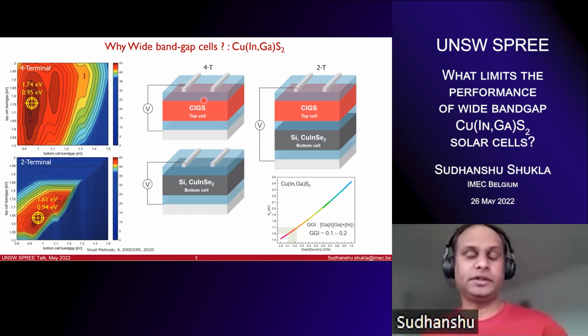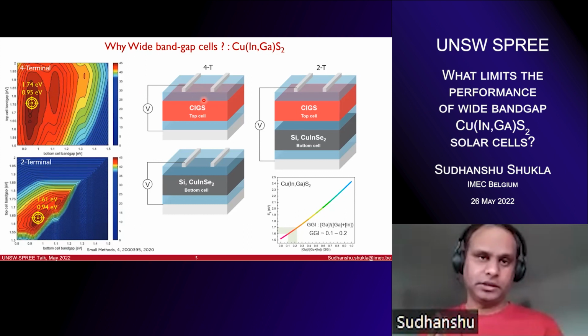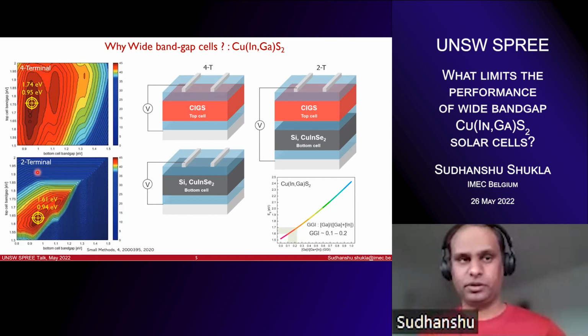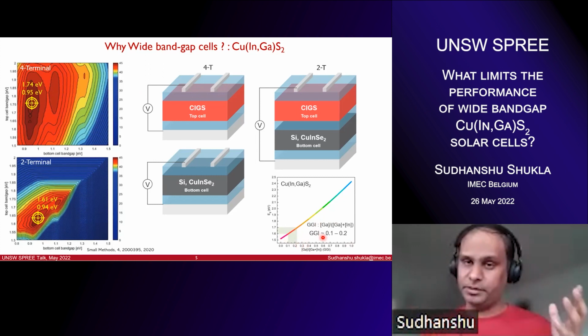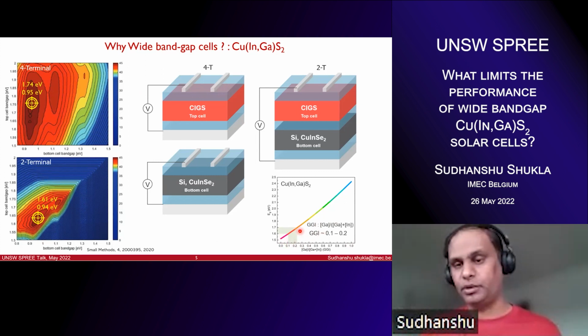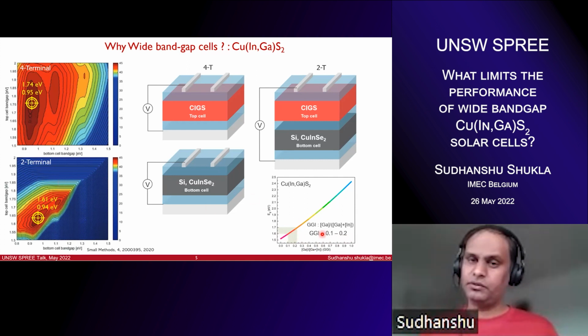Of course, we have perovskites and there is extensive research going on, but the problem that I want to emphasize today applies to perovskites as well, as you will see in the next slide. But this slide tells you that by using copper indium disulfide, you can obtain this band gap of 1.6 to 1.7 eV by introducing gallium, this is the GGI, in the copper indium gallium sulfide lattice. If you incorporate more and more gallium, you can increase the band gap all the way from 1.5 to 2.4 eV. And with very low quantities of gallium, I'm talking about 0.1 to 0.2, you can get this desired band gap. This is very nice compared to selenide, because for selenides, the same band gap you will obtain only if you have gallium more than 0.3.